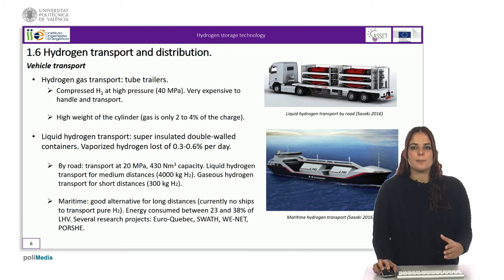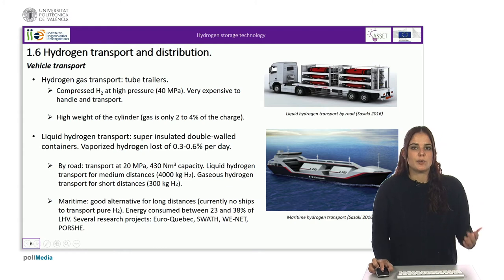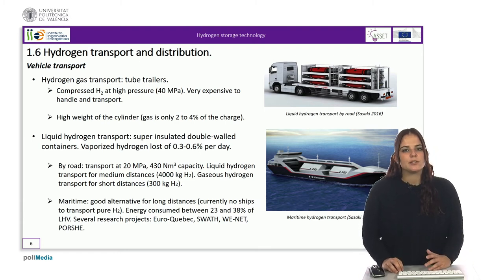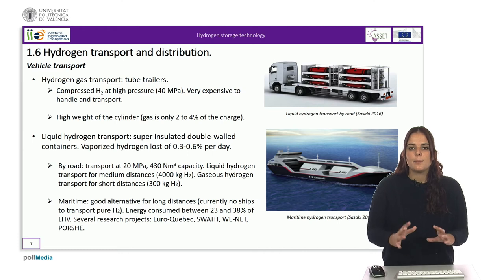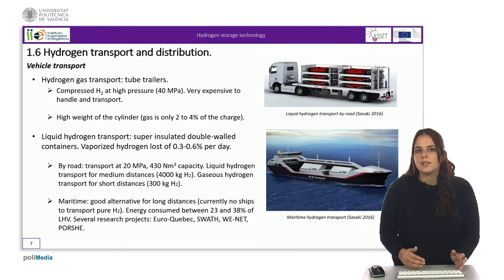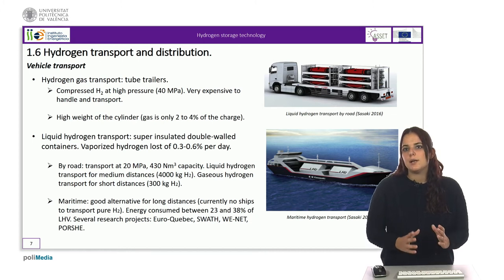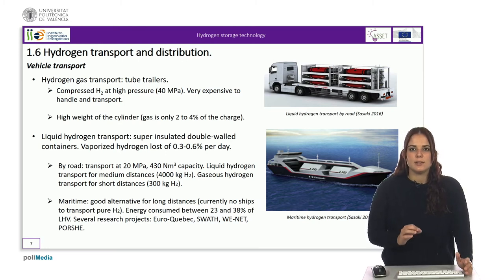Hydrogen gas transport by road can be done using tube trailers, as shown in the figure. If hydrogen is transported as gas, it must be compressed at very high pressure in order to optimize the capacity of the containers. High-pressure cylinders operate at around 40 MPa and can hold about 1.8 kg of hydrogen. However, they are expensive to handle and transport. Tube trailers, which consist of several steel cylinders mounted on a protective frame, can be configured to transport from 60 to 450 kg of hydrogen depending on the number of tubes. This design is very inefficient in terms of energy transported, as the weight of the cylinders means the gas represents only 2–4% of the total weight.